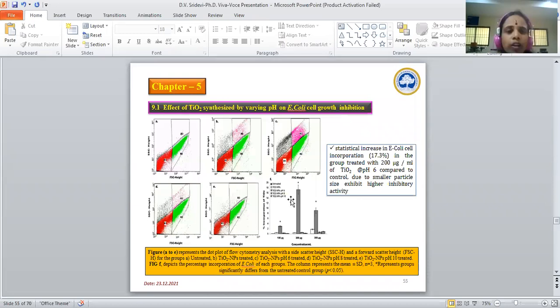In this slide, you can see the effect of TiO2 nanoparticles synthesized by varying pH on E. coli cell growth inhibition. Generally, bacterial growth inhibition can be determined by FACS analysis, the flow cytometer analysis. Flow cytometry is a technique used in eukaryotic cells to determine the cell viability and metabolism of synthesized nanoparticles. Figures A to E represent dot plots of flow cytometry analysis with side scatter light and forward scatter light. From the histogram, it was observed that there is a statistical increase in E. coli cell incorporation, that is 17.3% incorporation was observed with TiO2 nanoparticles synthesized at pH 6 at a concentration of 200 microgram per ml. This is because smaller particle size exhibits higher inhibitory activity.